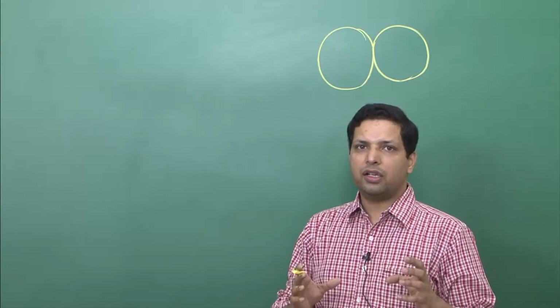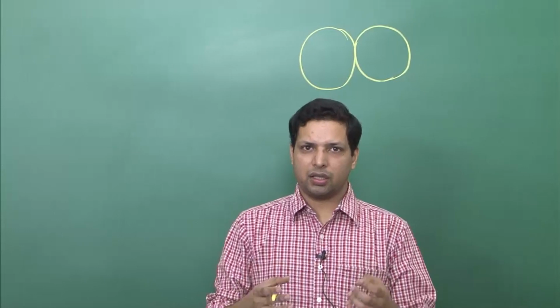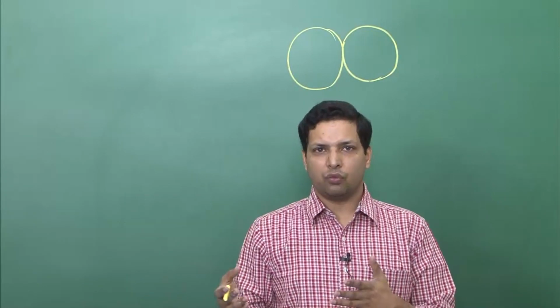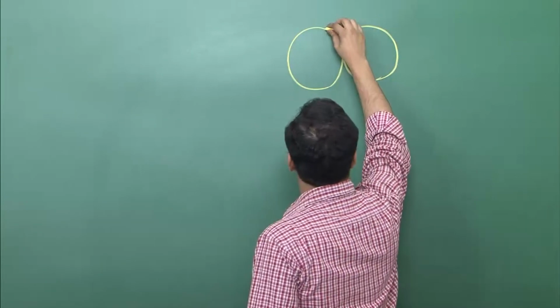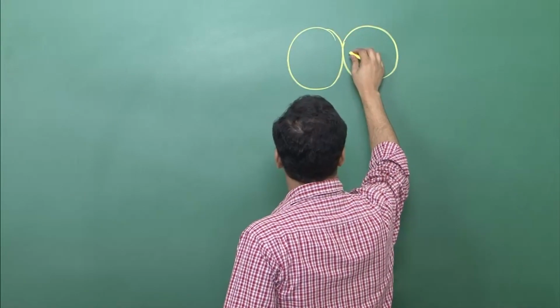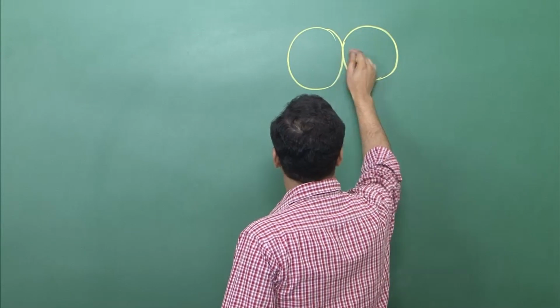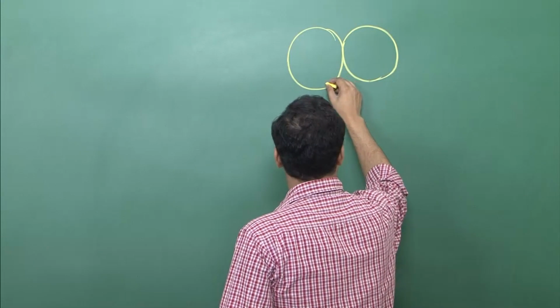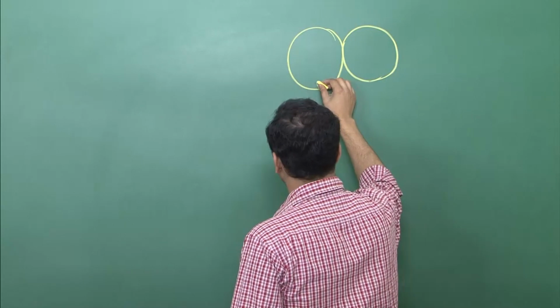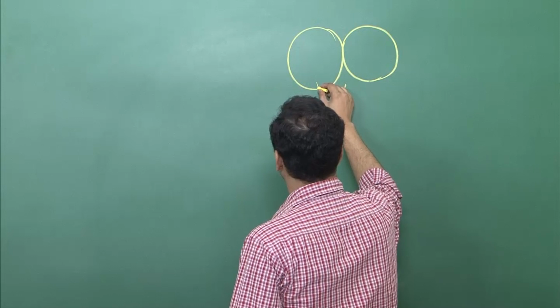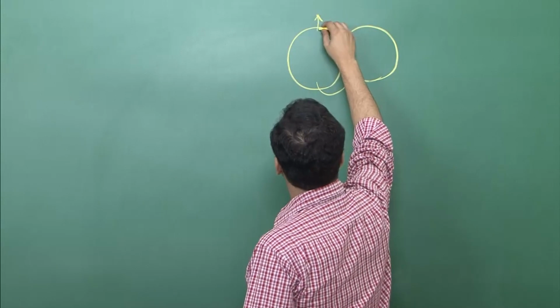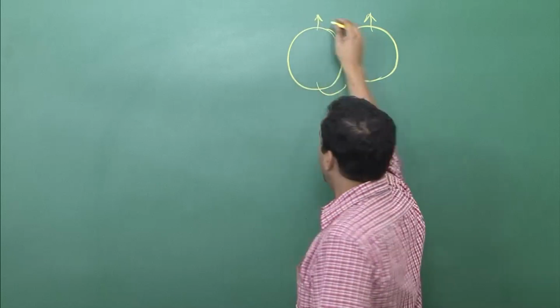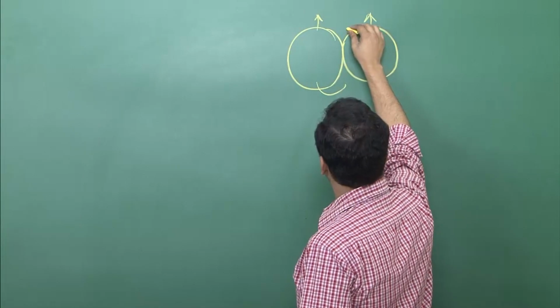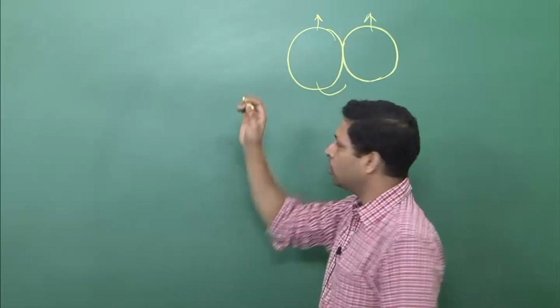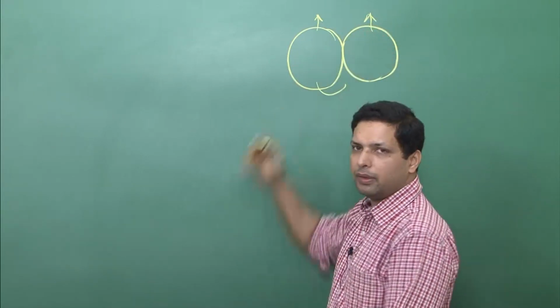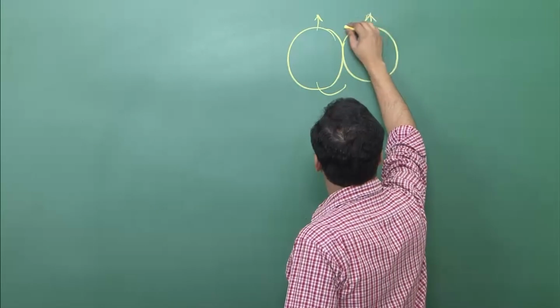In general we will start with sintering of two particulates, and this is the same principle that will get extended when you have more than two particulates. So, let us say somewhere over here, when you want to coalesce, these two particles should combine and become one. This can happen by material mass flow taking place by evaporation and condensation. So, something from here will evaporate, and then where should it condense? We want to coalesce the two particles. So, there should be growth in the neck, or basically the neck should disappear,